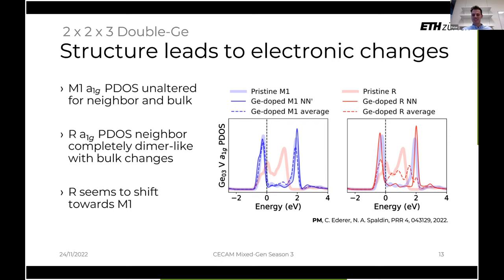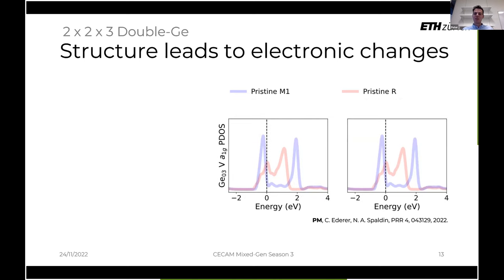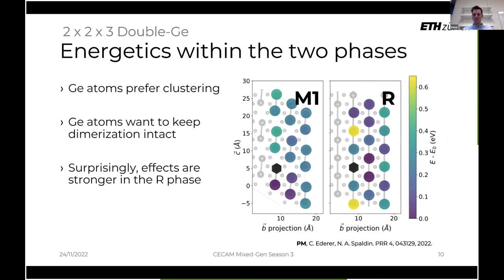Thank you very much for such a question. So first, before I answer, I would like to note that it is rather difficult to draw conclusions between the relative stabilities or relative effects on these two phases, on the rutile and monoclinic phases, because using conventional DFT, as you probably know, the energetic differences between the monoclinic and rutile phases are incorrect. So indeed, normal DFT predicts that the rutile phase is lower in energy than the monoclinic phase, which makes direct comparisons between any energies of one phase to the energies of the other phase rather problematic. And this is also the reason why going forward, we would like to use more involved methods to have a tool to directly compare these two phases.